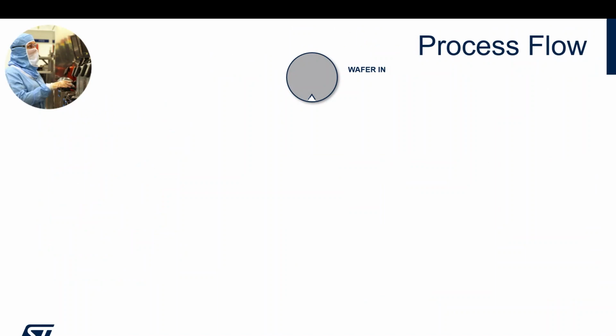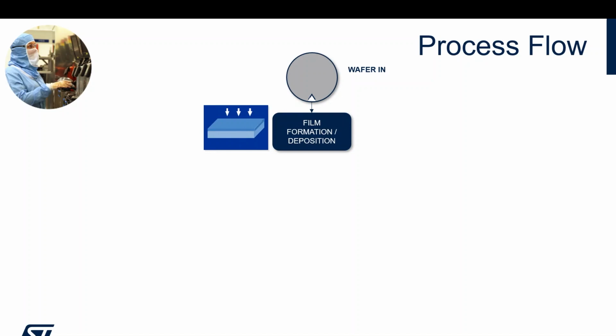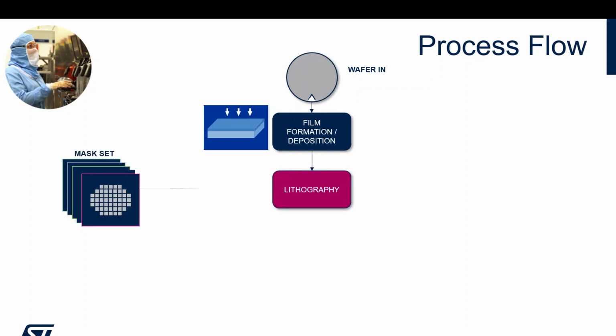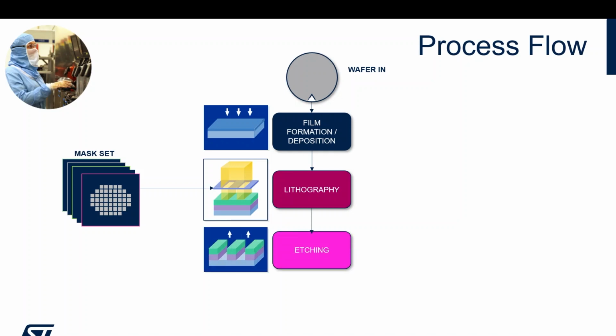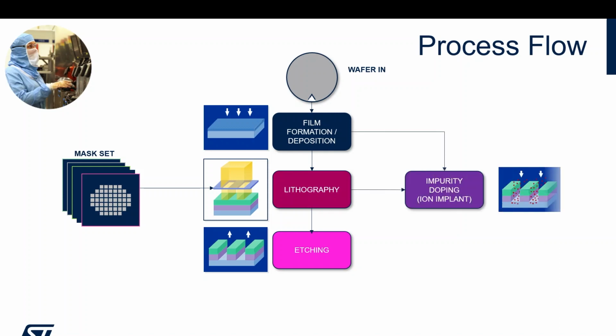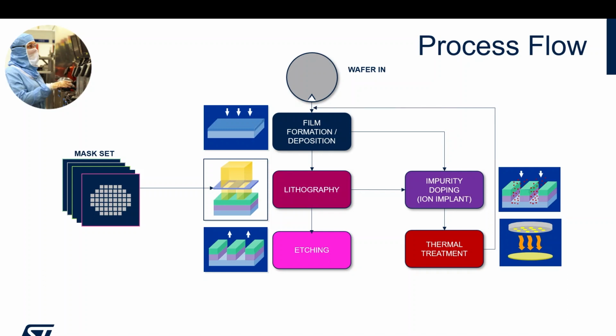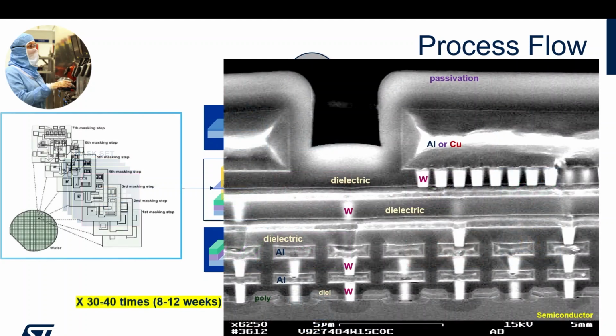And going to the process flow, you start from the wafer in. You do, for example, film formation, like epitaxy or the deposition of a dielectric. Then you make a lithography, so you define exactly the structure that you want. You do some etching in order to remove the part which should be removed for fabricating your structure. Then again you go to ion implantation doping, and then thermal treatment, and you repeat the process, depending on the complexity of your devices, several times in order to achieve very complex structures like this, for example.